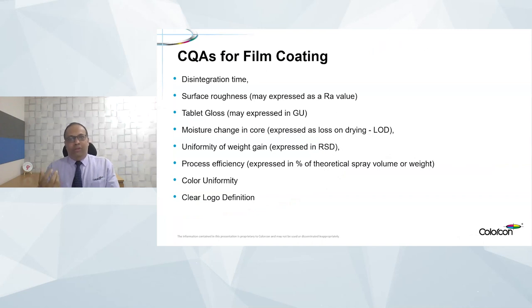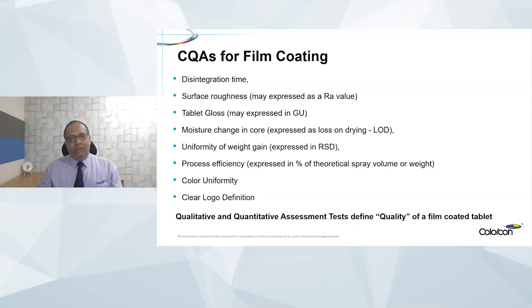Most of the time, if we were to list the quality attributes for the final tablet, we would talk about the appearance, but beyond that, for an immediate release coating system, it needs to have a good disintegration time, surface roughness, gloss, and moisture change, that is the LOD we were talking about in the CFM example. Also uniformity of weight gain in terms of RSD, especially important when we are doing active coating applications, and also important from the perspective of color uniformity. Process efficiency in terms of the percentage weight gain versus the actual applied spray, color uniformity and clear logo definition become important quality attributes because we're talking about achieving a perfect finish. So perfect finish tablets have good gloss, a smooth surface, very good color uniformity, clear logo definition, and good weight uniformity. These are qualitative terms, but in some cases you could quantify some of these aspects to make sure there is indeed an assessment of the film coating quality.